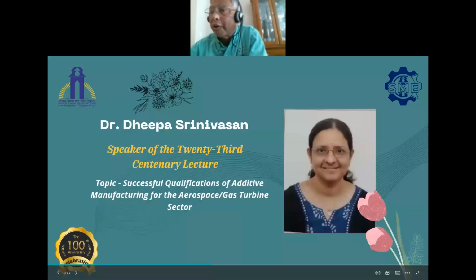A lot of the problems we are seeing in terms of 10 to 30 micron particle size, and trying to melt them and coalesce them and take out the heat treatment, bonding, and joining those things, and taking care of the metallurgical issues like thermal stress, will probably go away if we can magically do it.